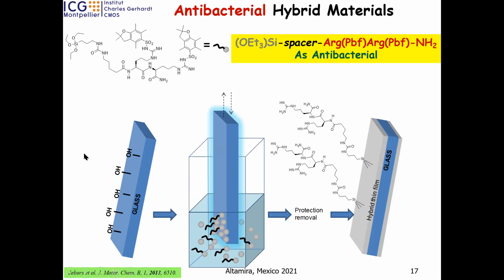And now we took glass, classical glass, and you put it by dip coating in the solution and you withdraw. You can control the thickness. If you remove it very fast, the thickness is high. If you remove it very slow, the thickness is very thin. It's like honey. If you take a spoon and put it in the honey and remove, you remove a lot of honey. It's something like this.